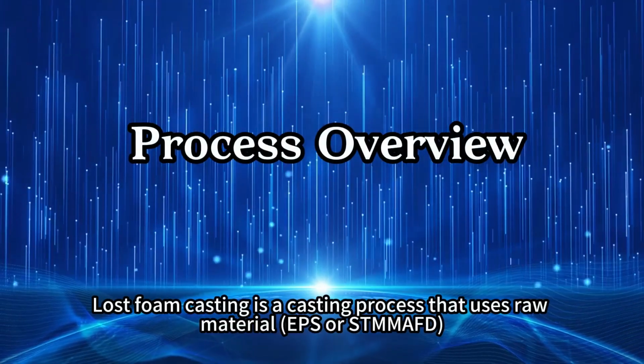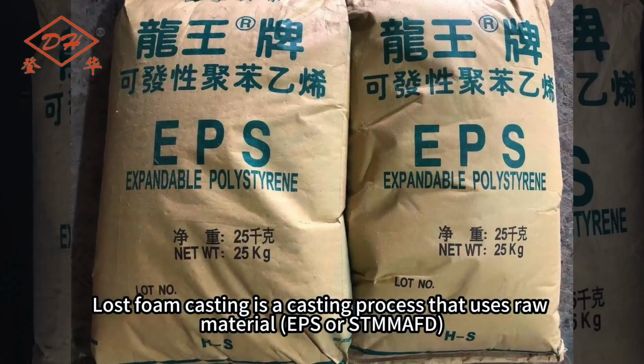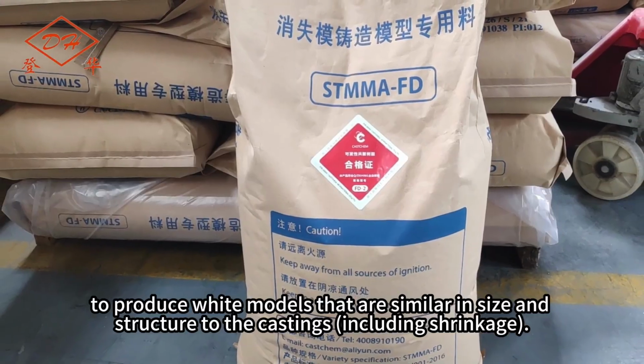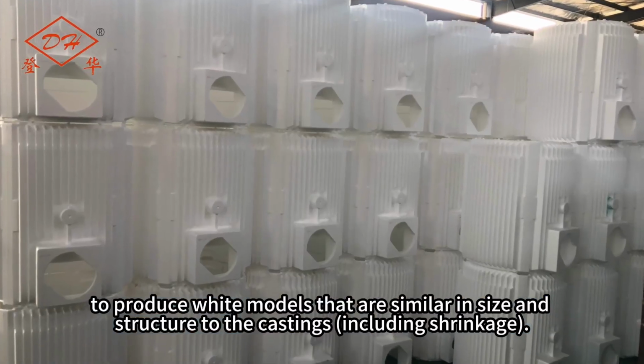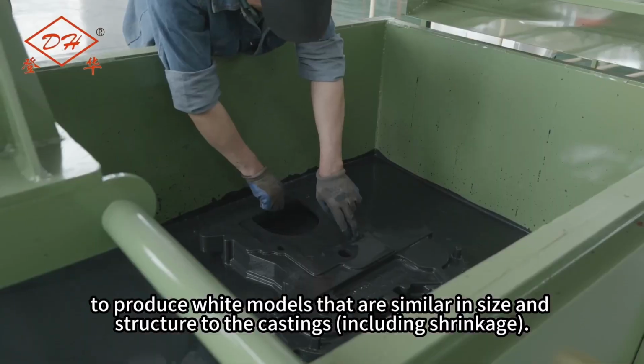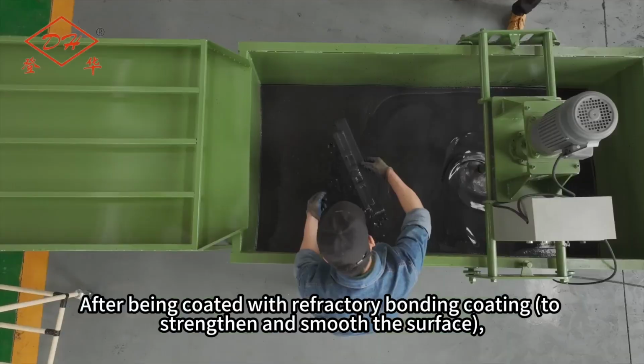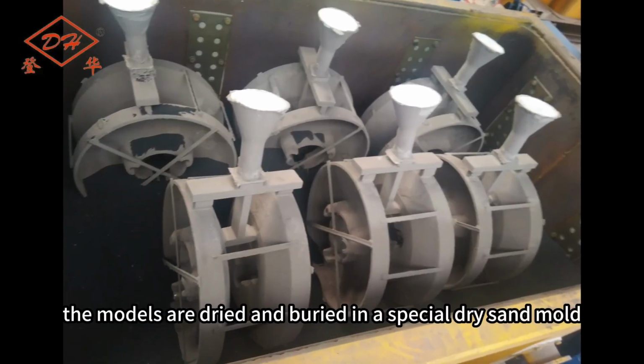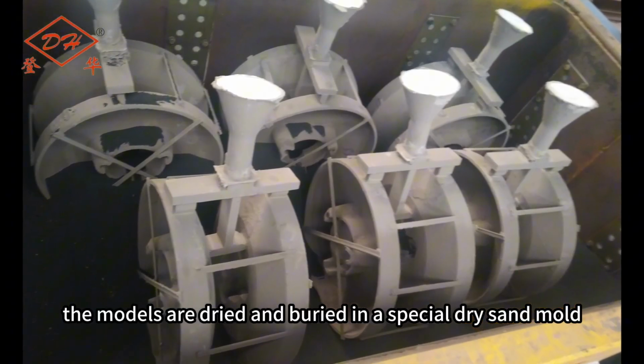Lost foam casting is a casting process that uses raw material EPS or STMMA to produce white models that are similar in size and structure to the castings, including shrinkage. After being coated with refractory bonding coating to strengthen and smooth the surface, the models are dried and buried in a special dry sand mold.